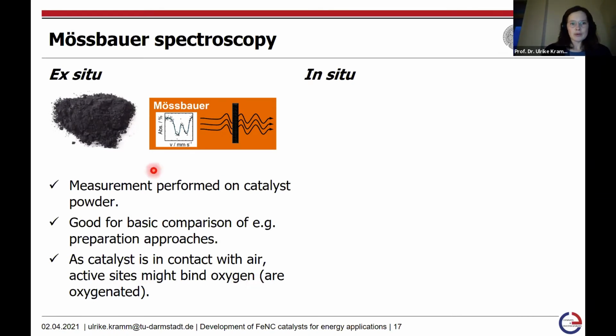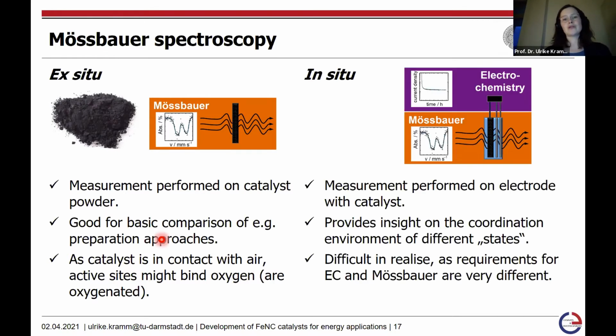Besides ex situ Mössbauer spectroscopy, that, as I mentioned, helps to distinguish the different preparation approaches and, let's say, to see which one looks more optimal, we can also go for in situ Mössbauer spectroscopy, and that means a coupling of Mössbauer spectroscopy with electrochemistry. In this case, the measurements are performed on the catalyst under applied conditions, different potentials, for instance, or maybe even different gas atmospheres. And based on that, we might be able to identify different coordination environments for the different states of operation within our experiment.